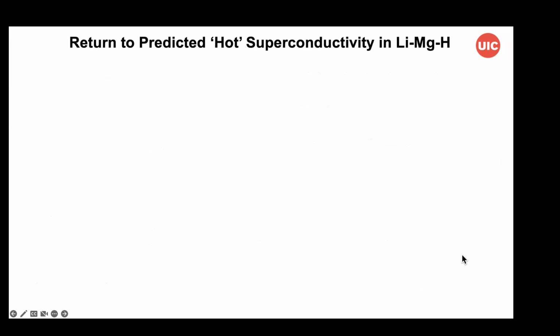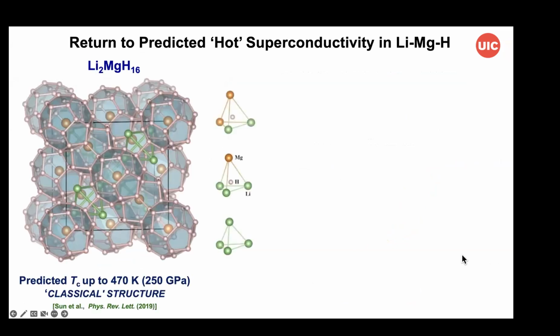But I want to return to the Li-Mg-H system and the predicted TC in this material, because this goes to the whole question of a mechanism and the need to go perhaps beyond what we're currently doing theoretically to really get at the nature of these materials. So if you look at this interesting material that was predicted by the Jilin University group with this very high TC, this very highly symmetric structure. It has these interesting tetrahedral sites, and some of them are filled with hydrogen, some are not. And this idea gave rise to the notion that there could be hopping between the sites, both in a classical sense at the temperatures of interest, that is where one has high temperature superconductivity, and at low temperatures due to